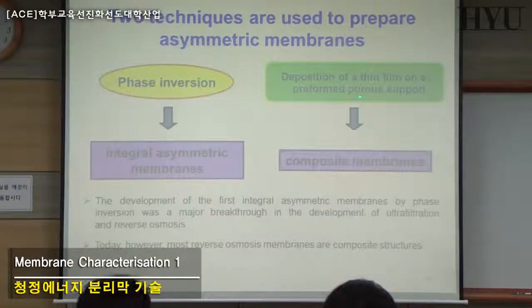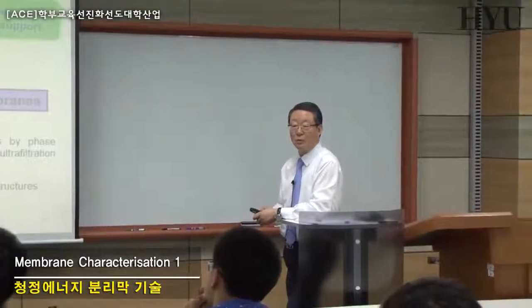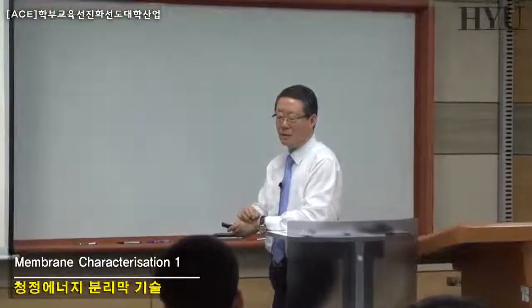Then we have to prepare two different layers. The first layer is a porous support layer, and the second layer might be the very thin selective layer. Usually the thickness of the skin layer might be less than 1 micrometer, usually less than 0.1 micrometer. The thickness of the composite membrane in water treatment is known to be about 0.2 micrometer, and the integrally skinned hollow fiber membrane, if it's used in enriching nitrogen gas from air, is about 0.04 micrometer. Okay, 0.04 micrometer, in other words 40 nanometer, and a 40 nanometer skin layer is very common in the gas separation area, whereas about 200 nanometer is common in water treatment areas.